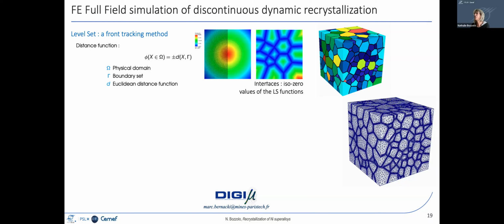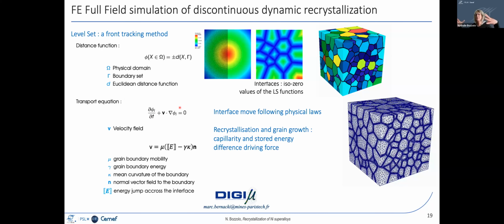So in these models, each grain is described with a level set function. This level set function is positive inside the grains, negative outside, so that the interface of the grain boundary is actually the iso-zero value of the level set function. Then we need a transport equation to make this function evolve, vary, and to represent the movement of interfaces. So this is a transport equation which is used, and in this transport equation we have a velocity field to be defined, and this is where the physics are